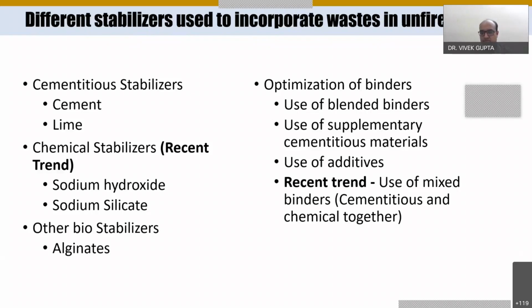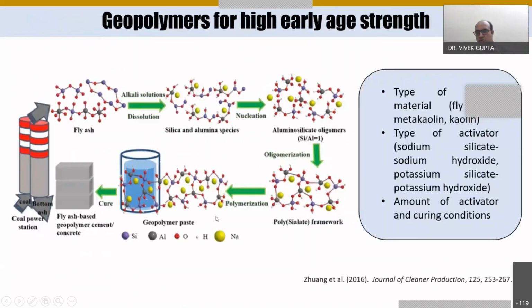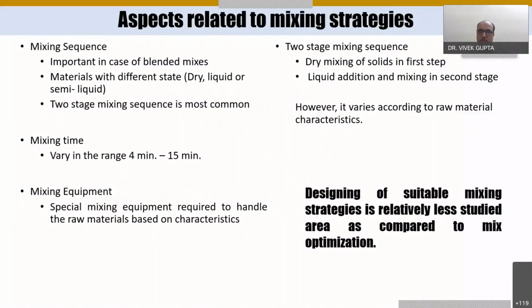Then these are the geopolymers which recent researchers are using for the high early strength, and these are the different types of source material they are trying, like the fly ash, metakaolin, and the type of activator. The majority of researchers have used sodium silicate or sodium hydroxide, but some of the studies have also attempted potassium silicate, potassium hydroxide, and sodium carbonate. Then the amount of activator and the curing condition can be explored, like what could be the optimum amount of activator, and what could be the best curing conditions if we are going with the geopolymers. Then these are the different aspects related to mixing strategy.